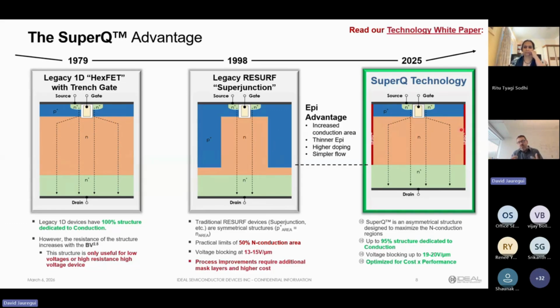So you can see geometrically, we can have high dopant and very wide mesas to improve the conductivity and therefore reduce the on resistance. A second order benefit is that we don't need this little buffer layer that these guys have, which they use for robustness purposes. We don't need it, so that means we can have a thinner epitaxial layer. And then finally, our ability to block voltage is around 18 or 19 volts to 20 volts per micron, improving on what was being done back then.